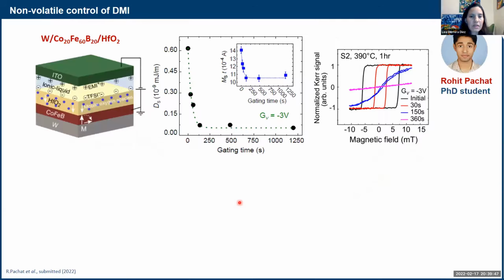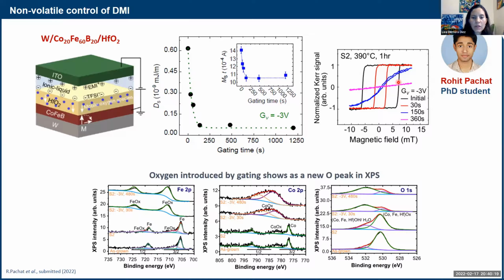A similar result was obtained with tungsten, cobalt, iron, boron, hafnium oxide. Here we can see the DMI decreasing as a function of the gating time for -3 volts. The difference here is that we started from a PMA state because we had to anneal the system to see PMA. So then we had this PMA state that gradually goes in plane because it gets over-oxidized. This time we start from PMA and we over-oxidize. And this is the study that I showed you already.